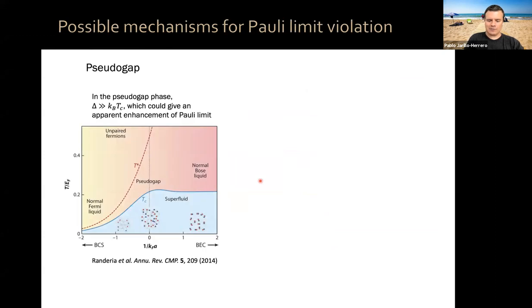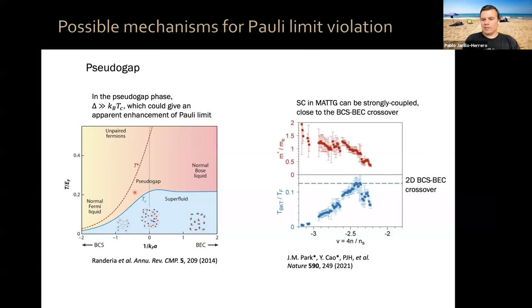Now, you can also have preformed pairs, which can manifest themselves as a pseudo gap that can happen in the strong coupling regime. Remember, because in our system we're close to the BEC to BCS crossover, it could be that we have gap values which are much, much larger than what the KBTC formula, the BCS formula, would give you, okay? So in our case, in the region where we're in a strong coupling limit, that's likely the case.